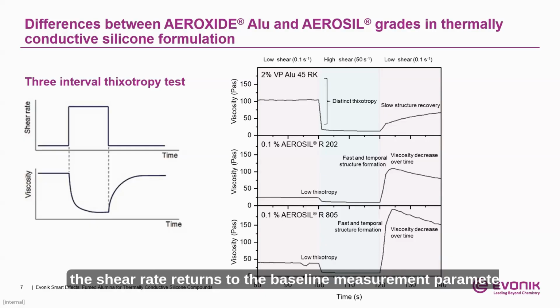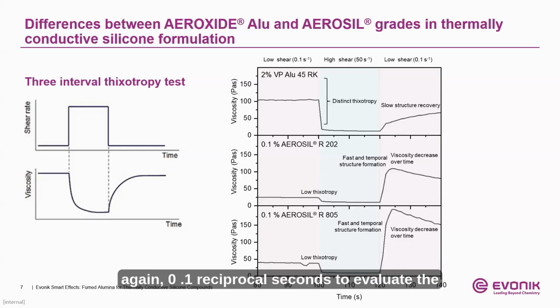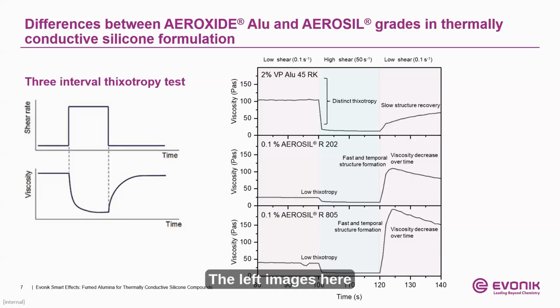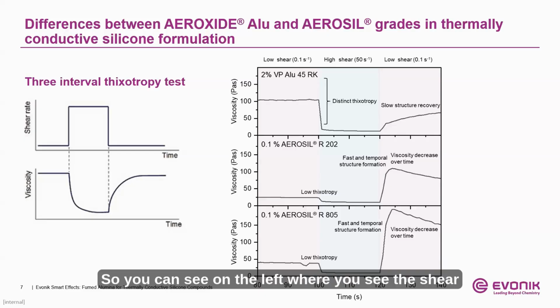From here, the shear rate returns to the baseline measurement parameter, again, 0.1 reciprocal seconds, to evaluate the post-shear recovery of the material, how much the viscosity will recover once the high shear condition has been removed. The left images here give you a correlation between the typical viscoelastic behavior in relation to the shear rate during the evaluation. On the left, where you see the shear rate axis, you begin at a very low shear rate, go up to a very high shear rate, and back down to low.